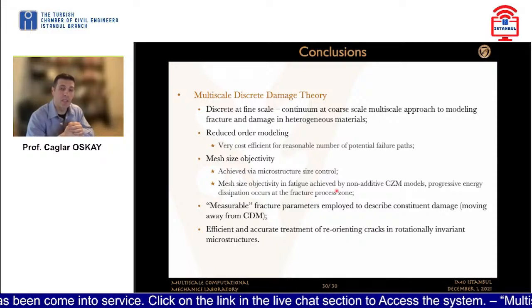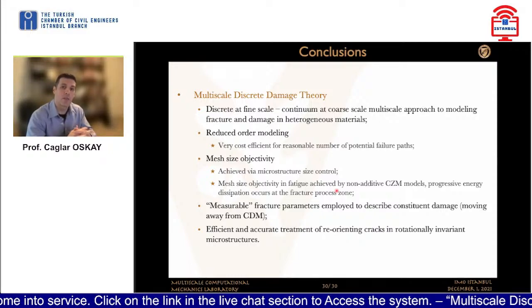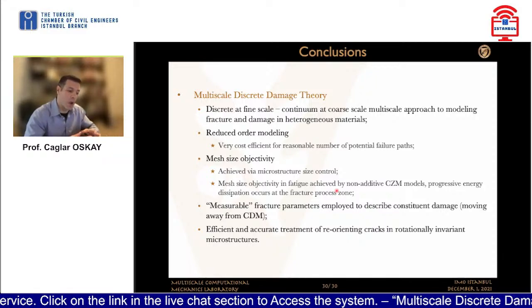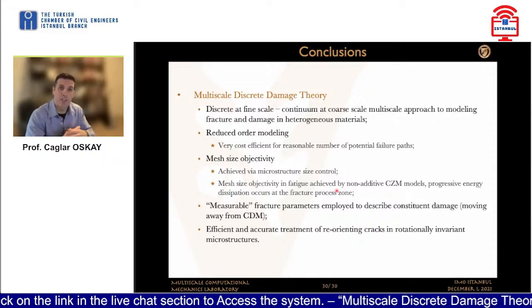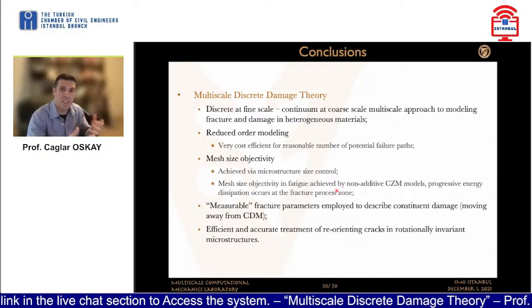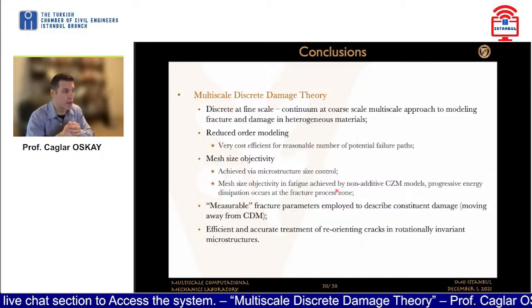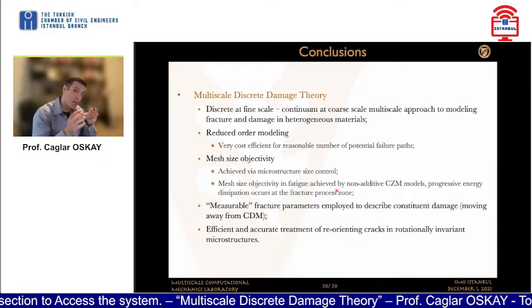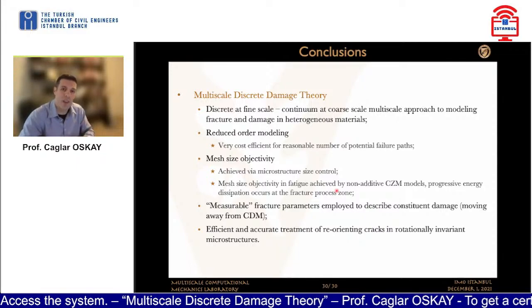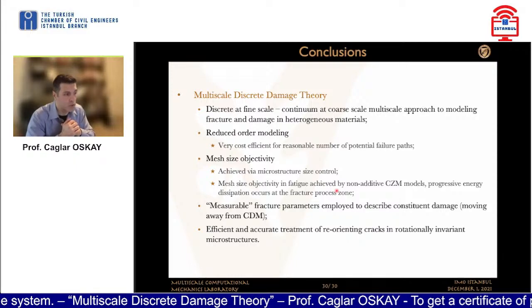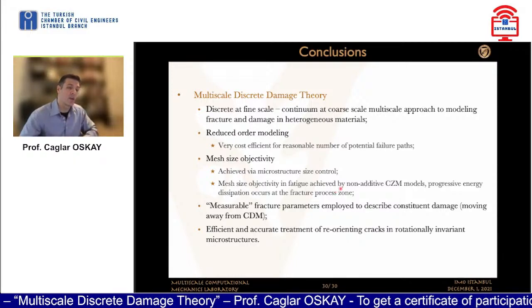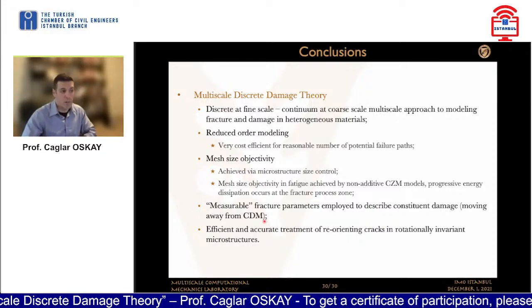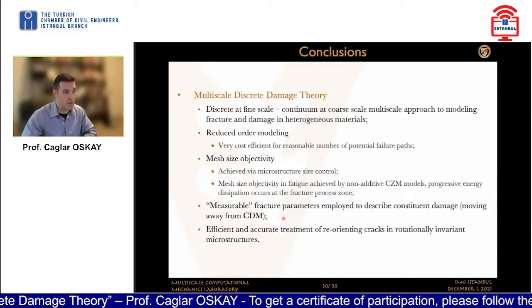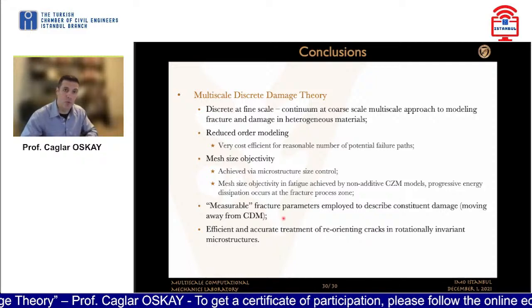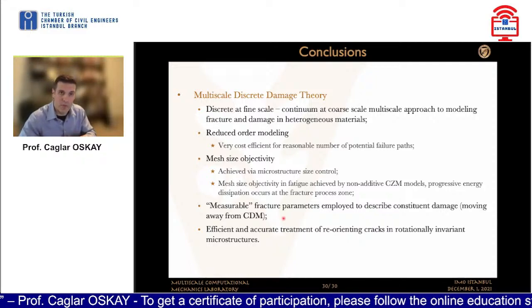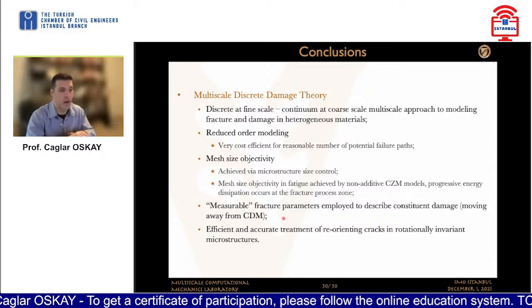And even though it models the damage behavior in a way that is diffuse at the macroscopic scale, because of our focus on mesh size objectivity, we do not see significant mesh size effects in the model predictions. Because we are going down to the scale of the microstructure and creating a fracture-based representation at that scale, we are able to use fracture parameters measurable from experiments in describing the constituent damage models. And it also allows us to go beyond the more straightforward failure patterns and be able to characterize reoriented cracks and so on and so forth.